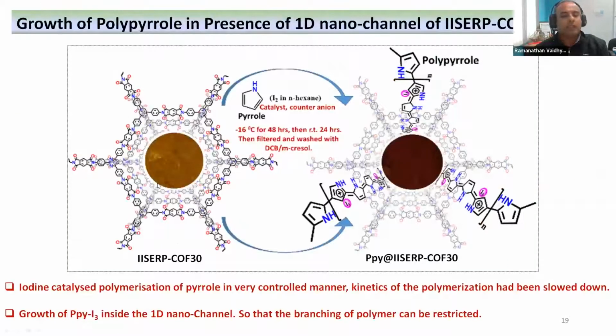With that, you can see here, then what we do, to improve the electronic conductivity of this COF, we grow polypyrrole into the pores of the COF. And this also has some design aspect to it. So the polypyrrole can exist in two forms. Either it can be a linear chain or it can be a cross-linked polymer. Only the linear chain form of the polypyrrole has high electronic conductivity. So we naturally identified that the narrow one-dimensional pores of the COF will favor the growth of linear polymer rather than a cross-linked polymer. And this is what we believe is happening.